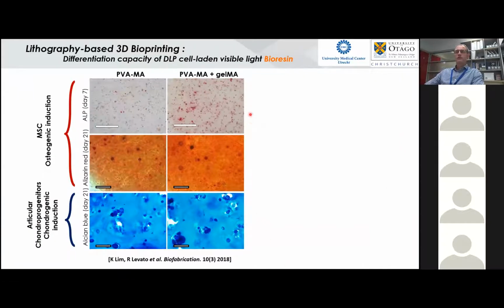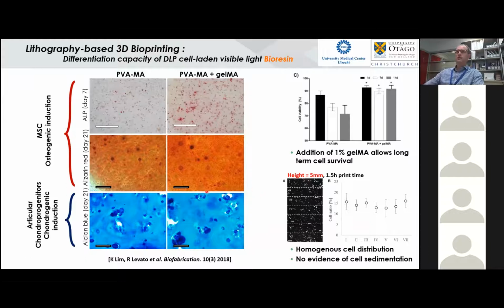But I think one of the interesting things we did in this early work, and this was also done with Ricardo at UMCU, was also to try and show that when we incorporated cells into the process, not only were we able to maintain viability and see differentiation, but what we wanted to show as part of the layer by layer process was that we didn't end up with sedimentation. So this actually shows that we could print a relatively thick construct, and then we were trying to look at the cellular distribution throughout, and we ended up with a homogeneous distribution of cells throughout that cell-laden bioresin print.